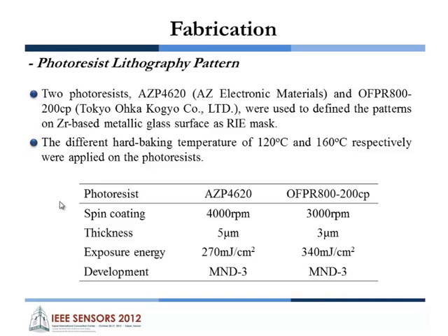For the photoresist lithography pattern, we use two kinds of photoresist to define the pattern on the zirconium-based metallic glass surface as the following RIE etch mask. Different hard baking temperatures were applied on the photoresist, and the parameters are shown here.